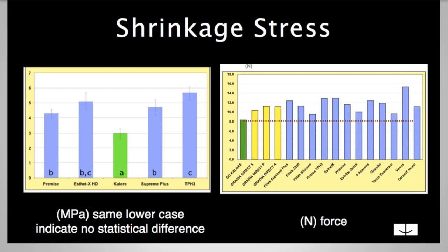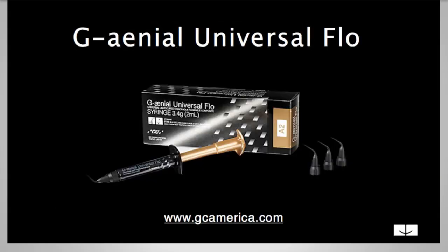What's interesting is that GC America wanted to create a flowable composite that's similar to a packable composite in a lot of characteristics. And so they came up with this new one called G-aenial Universal Flo. And so it had similar shrinkage stress that's very low, but also could wear well against opposing dentition. So you could use a flowable in areas where you would be using a packable.